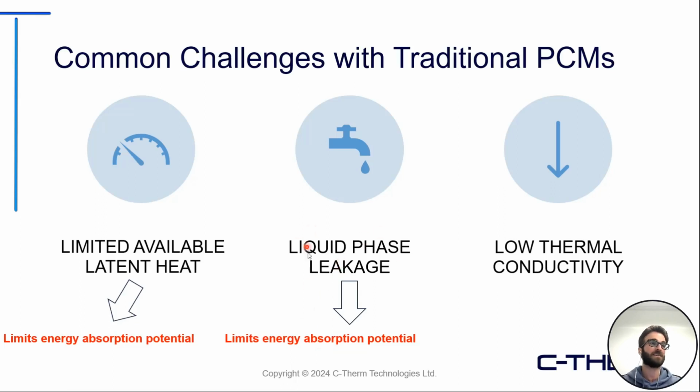This is actually an issue with regard to cycling. So as you go from solid to liquid state, you can have some issues there. And then low thermal conductivity. This impairs the heat transfer efficiency of the stored system. So once that energy is stored, it needs to be transferred to be used for whatever purpose that is, but the efficiency of that is an issue when you have low thermal conductivity. And this is the one that we're going to be taking a look at here today.